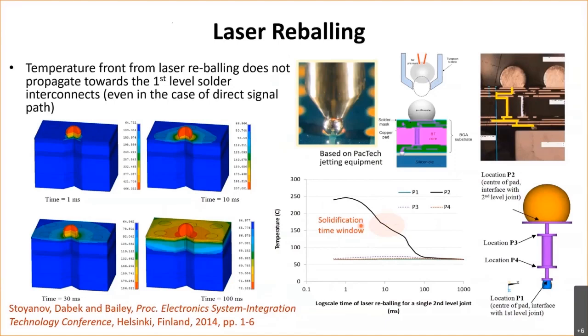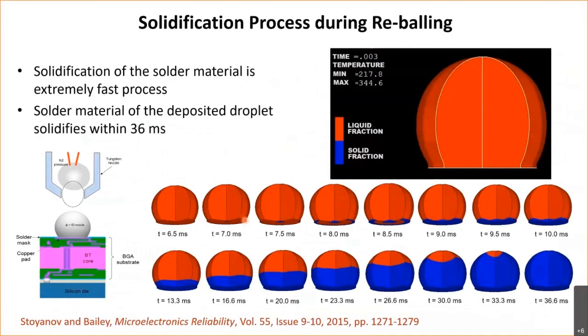And also you can see here where the solidification window is, and understanding how solder joints solidify. There's an example of a simulation here where a droplet has been dropped onto the pad. And you can see how the solidification front moves up that liquid solder droplet over time. So here we're moving into not just thermal and mechanical, but phase change. So the sort of multi-physics type calculations that are quite important.